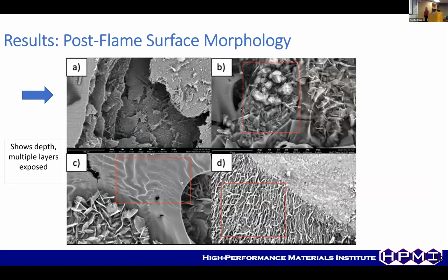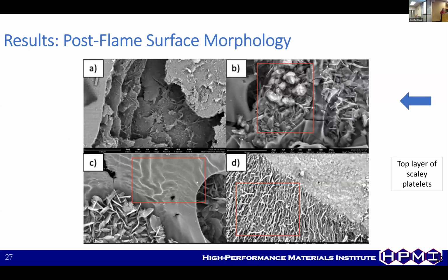So the results post flame test, surface morphology. We can see, showing depth, multiple layers. Even inside these one layer BNNTs, you actually have multiple layers inside of them, so you can see multiple layers are exposed. You do have charring up at the surface, and we have a scaly platelet on the top surface. We're going to do more investigation as to what that is in the future slides.